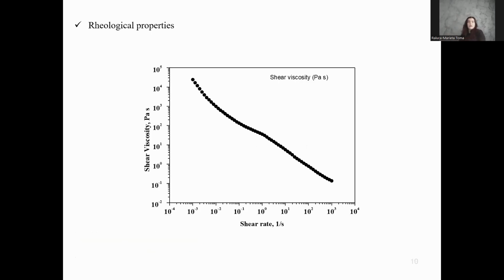Further, we investigate the rheological behavior, but here I would choose to present you the viscosity as a function of shear rate, which decreases with the shear rate at room temperature. This is normal for cream.